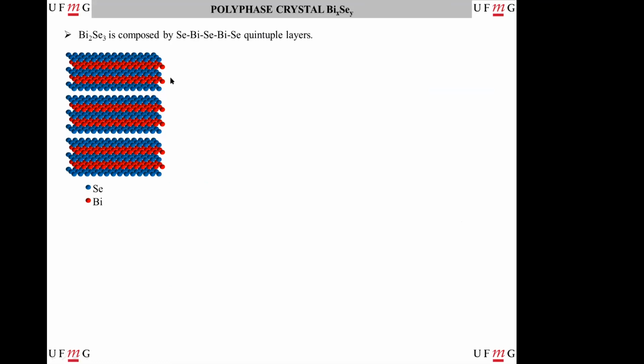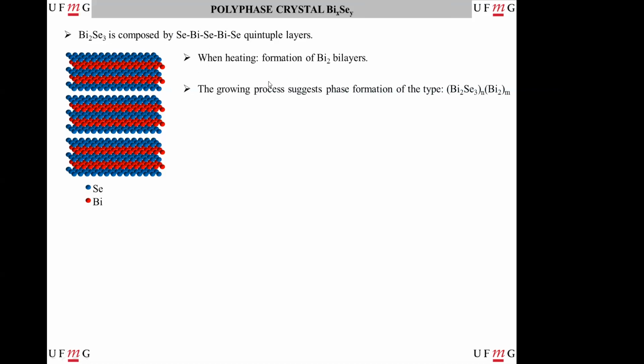But the thing is that when we heat this sample, the selenium, because it's lighter, starts to flow. So what happens is that there is the formation of bilayers of bismuth on the sample when we heat to a given temperature higher than almost 400 Kelvin. So we know that the growth process suggests that the phase formation of the system goes like this: a combination of quintuple layers of Bi2Se3 and bilayers of Bi2.